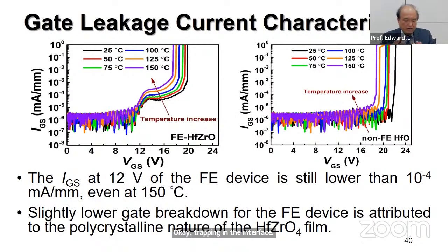And one of the concerns is, how reliable is this? This view graph shows the characteristics of the leakage and reliability of these devices. The gate leakage at 12 volt of the ferroelectric transistor is still lower than 10⁻⁴ milliamp per millimeter, even at 150 degrees C.